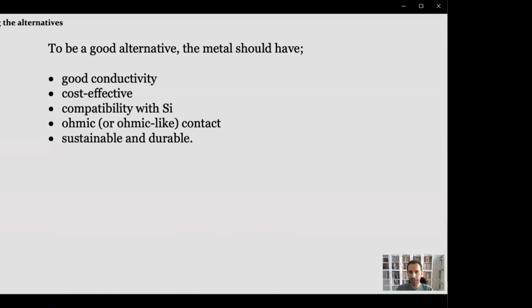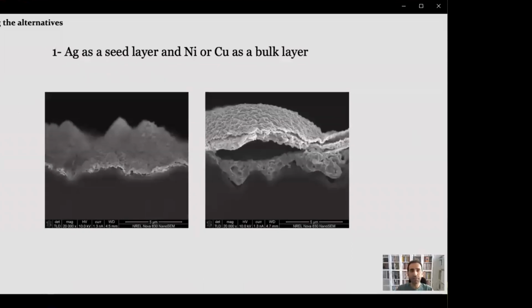Nickel and copper are surely cheaper than silver, and they have good conductivity. So let's look at how they work with the silicon. Here are SEM images of multi-layer printed contacts on a silicon solar cell. Since copper has an aggressive diffusion coefficient into silicon, and nickel has lower conductivity than silver and copper, they are generally used in a two-layer structure. Here, silver as a seed layer at the bottom, and nickel or copper as a bulk layer at the top are printed on a cell. This can be done either with two-step printing or printing the silver first and plating the bulk layer. Nevertheless, it is still using silver, which increases the cost.